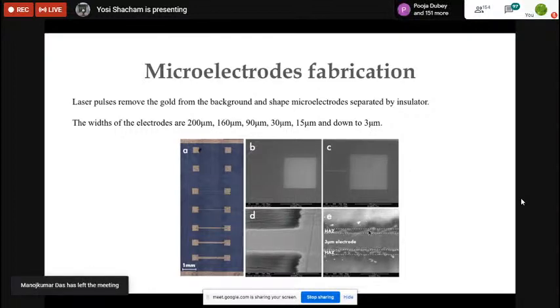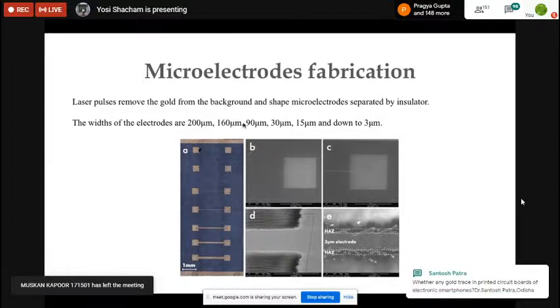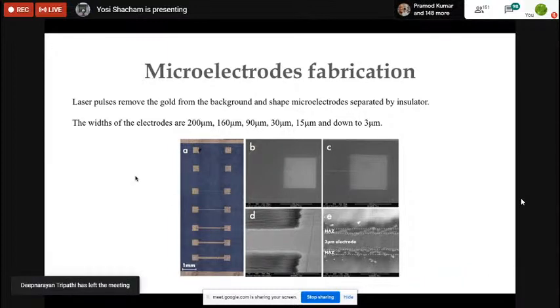This area here is called HAZ, heat affected zone. I told you there is no heating, but there's a little bit of heating. This heat affected zone is about 1 micron. So we can make 3 micron electrodes. Usually we don't need such electrodes. Most of the devices are 90 or 160 microns. This is how it looks.